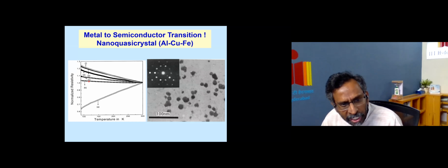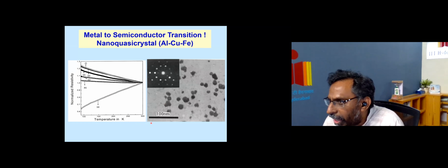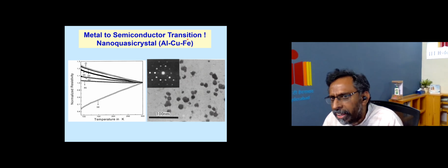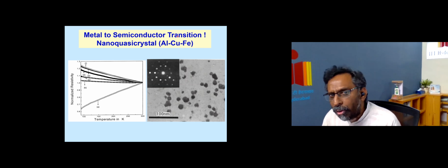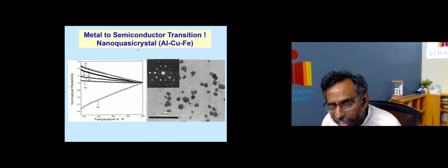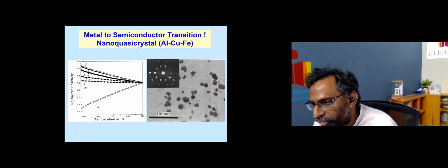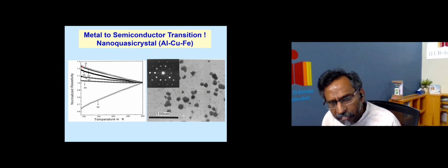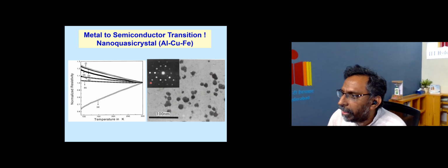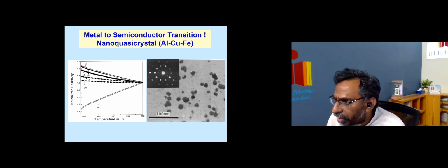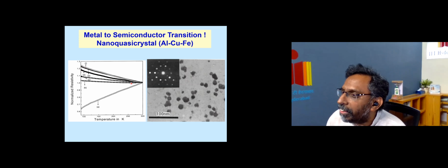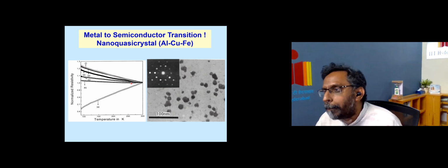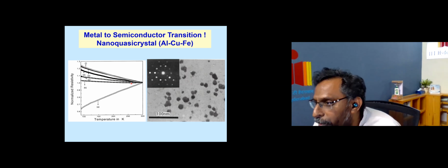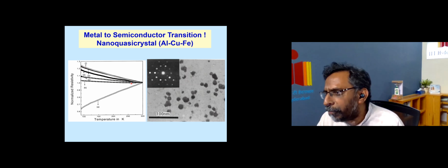This is exactly what you see in this particular curve, the increasing resistivity as a function of temperature. A typical metal such as aluminum, copper, iron will have such a thing. The moment I make this alloy in a nano form, what we call a nano quasi-crystalline form, a special structure it has, immediately you see a reverse trend. Resistivity is now decreasing with increasing temperature. That means a metal has become like a semiconductor now. This is the behavior of a semiconductor, we all know.